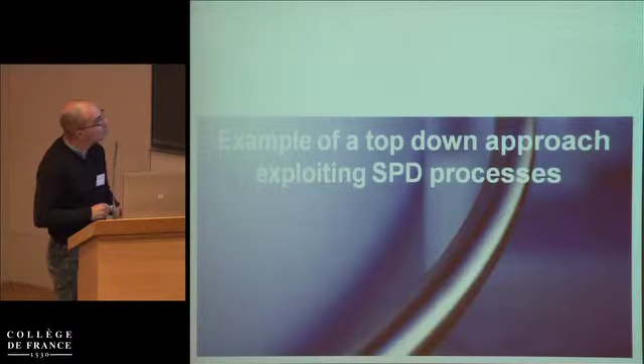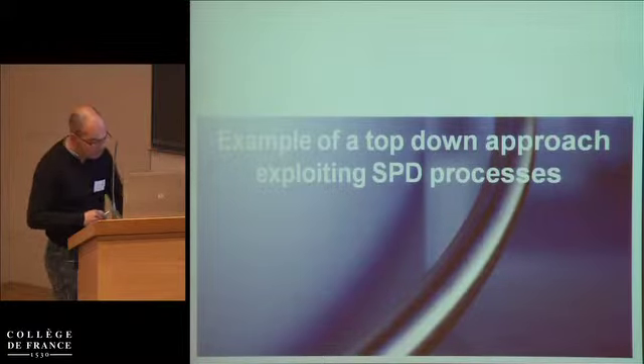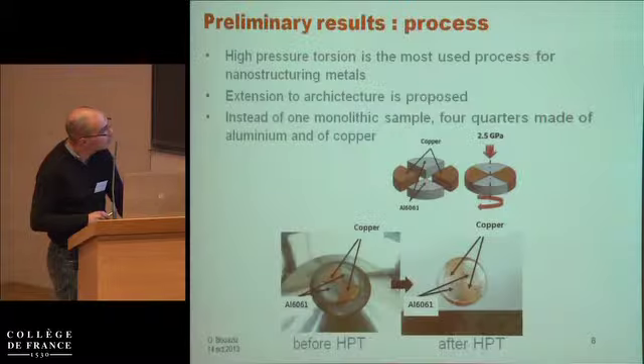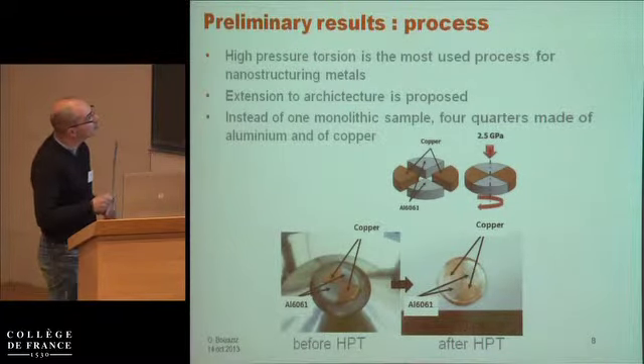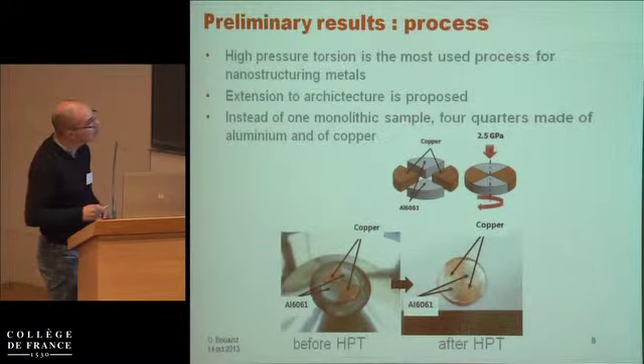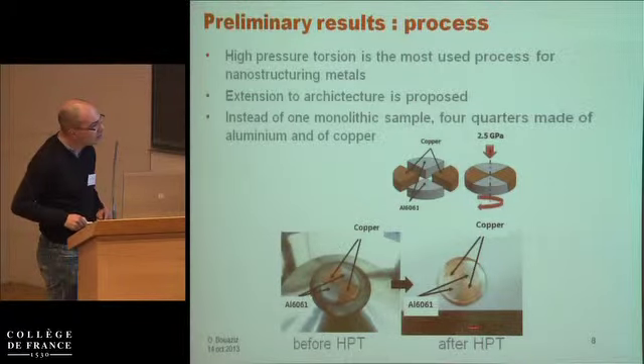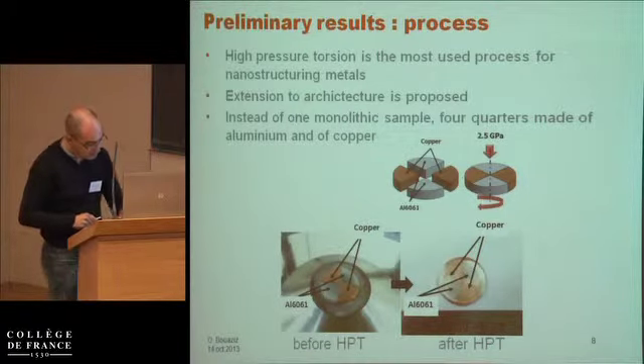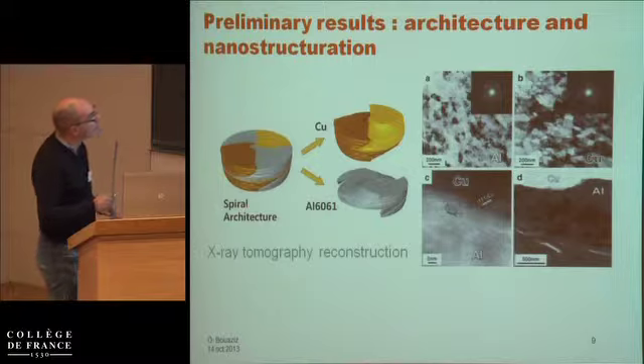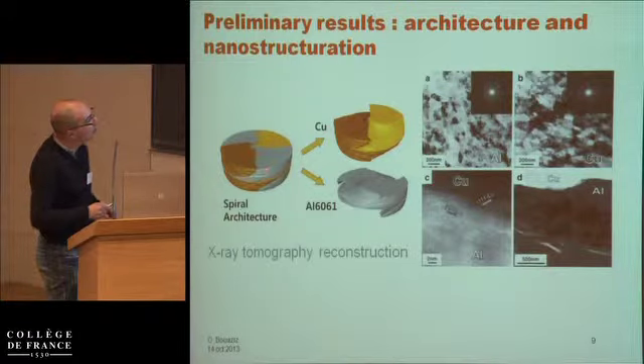So we want to exploit the severe plastic deformation process to architecture the material by a top-down approach. We have preliminary results using high-pressure torsion. Instead of one monolithic sample, we have used four quarters made of aluminum and copper in this combination. This is a sample before the HPT, and this is a sample after the high-pressure torsion. We obtain a sample where copper and aluminum are mechanically bonded, and by X-ray tomography reconstruction, we see that we have started to have a spiral-like interface.